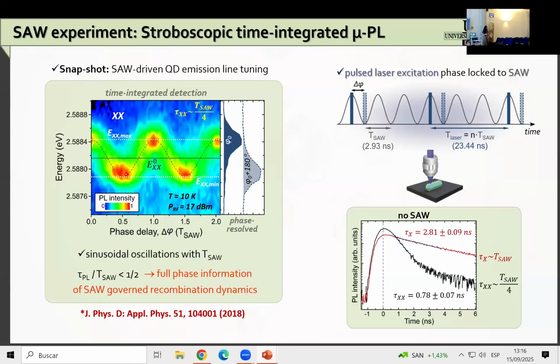And then when you deposit these nanowires on top of the acoustic wave, I guess the mechanical connection is better than in the flakes, because you have the splitting in the 2 lines. Well, the mechanical connection between the emitter and the substrate is of course a complicated topic. If you remember, there's this pyramidal top of the nanowires, and the quantum dot is positioned in this pyramidal top. So if the pyramidal top is not really touching the substrate, then the mechanical coupling is not so good. We observed that in the case of nanowires, which is why we also performed a similar experiment, but we encapsulated everything with polycrystalline zinc oxide done with RF sputtering at room temperature, not to damage the IDTs. And in that case, the coupling was perfect. All possible quantum dots that we could find in every nanowire were affected by the acoustic wave.